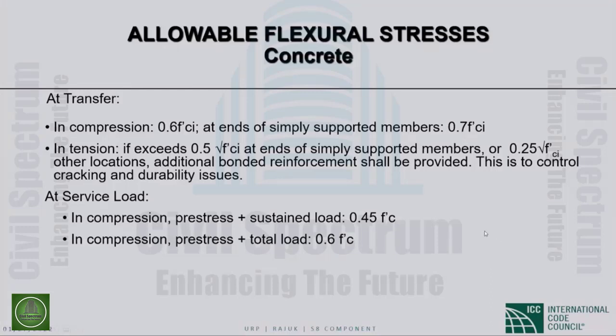If I'm looking at tension stresses, if we exceed 0.5 square root of f'ci at simply supported members, or 0.25 square root of f'ci at other locations, I'm interpreting this as meaning that this could be for continuous members where tension can appear at other locations besides the end of simply supported beams. We must provide bonded reinforcement, as I mentioned before. So that will hopefully address any kind of serviceability issues, cracking and durability issues.